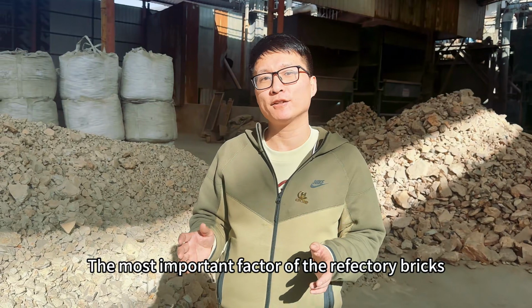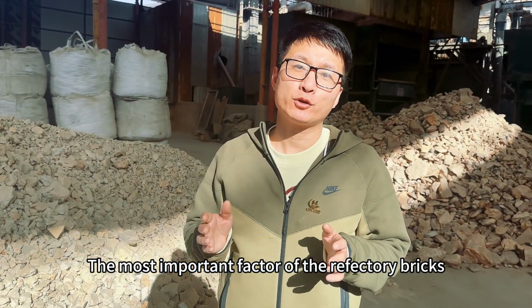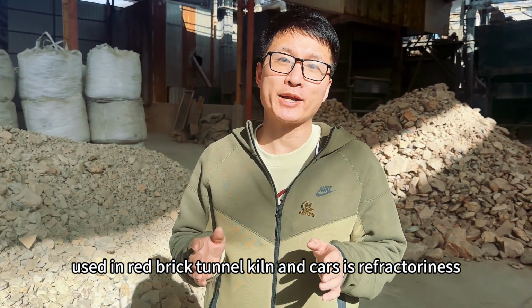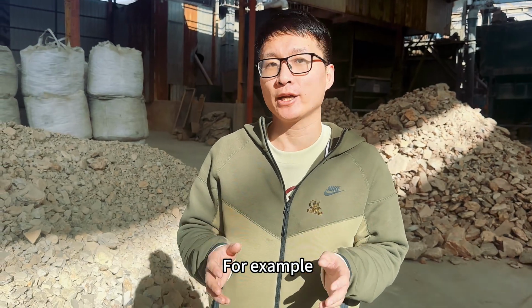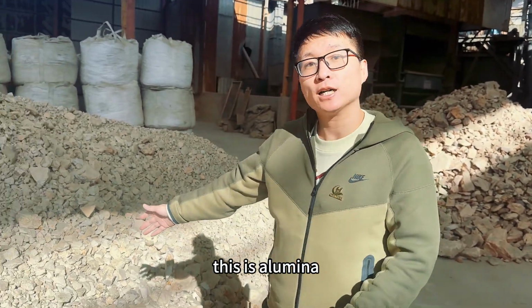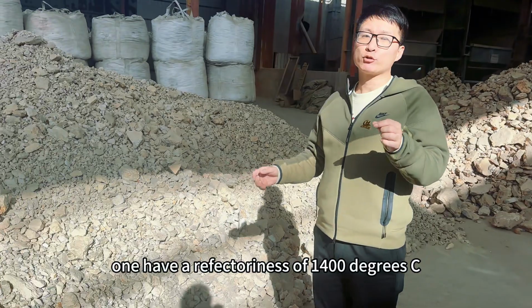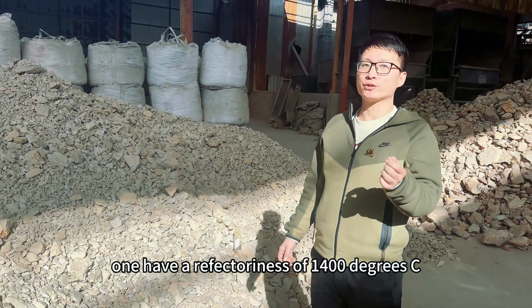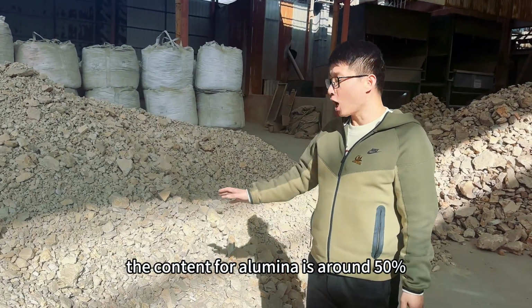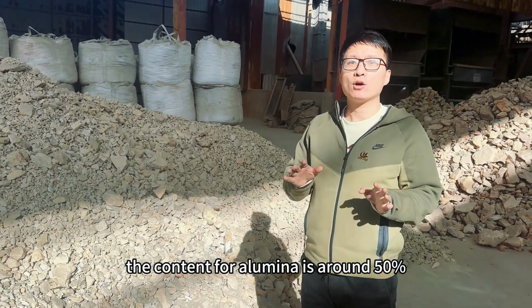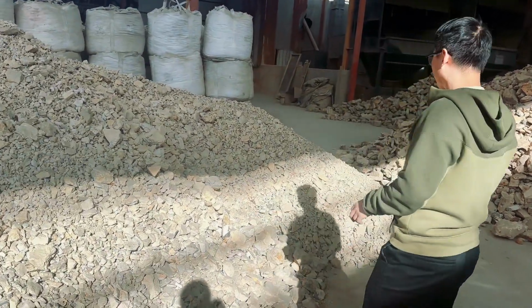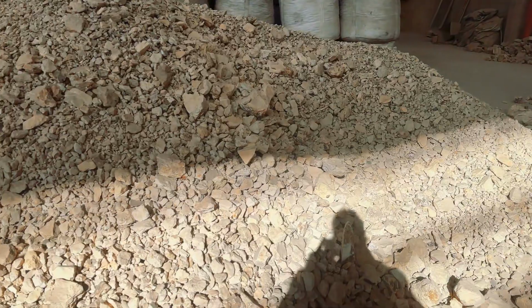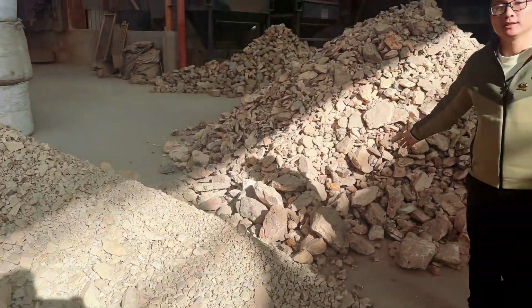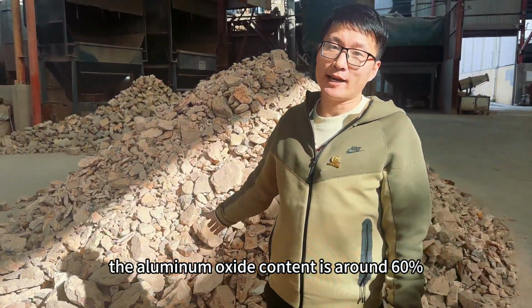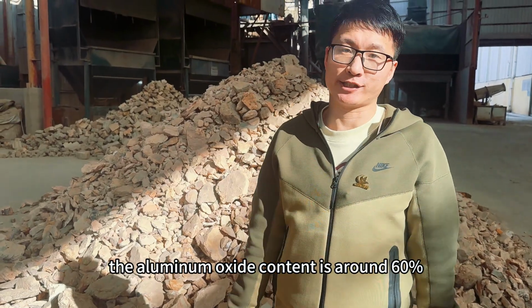The most important factor of the refractory bricks used in red brick tunnel kilns is the refractoriness. For example, this is the alumina. This one has a refractoriness of 1400 degrees C, and the alumina content is around 50%. But for this one, the aluminum oxide content is around 60%.